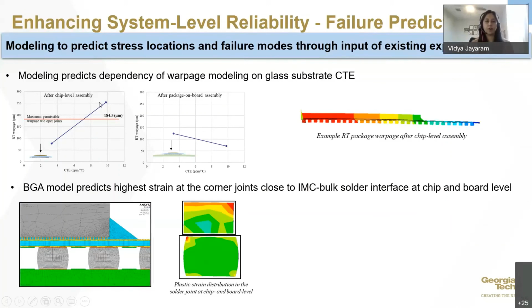So we modeled for warpage and we modeled for thermomechanical stresses. The warpage modeling had a couple of components to it. We modeled the warpage with different CTE of the glass interposer, and saw how the room temperature warpage was modulated accordingly. And this was at chip level assembly, and we also looked at after board level assembly, since it's critical to look at both, because something that impacts at chip level might have a worse effect on board level assembly. So board level, since our printed circuit boards are high CTE, overall the trend or the intensity of the change in warpage was lower compared to chip level, since there is a lower CTE mismatch here compared to chip level.